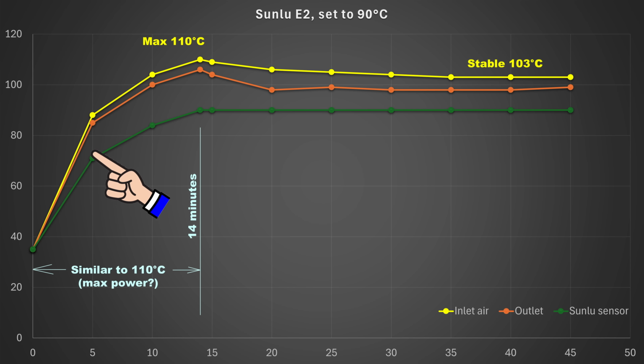Watching the left side of the curve, it is very similar to the previous one when I set the maximal temperature. And this means it starts with the heating at maximal power, and only when it reaches those 90 degrees Celsius according to its own sensor, it starts turning the heater on and off. But the problem is that the air reached that maximal temperature of 110 degrees Celsius, and only later it stabilized around 103 degrees Celsius.